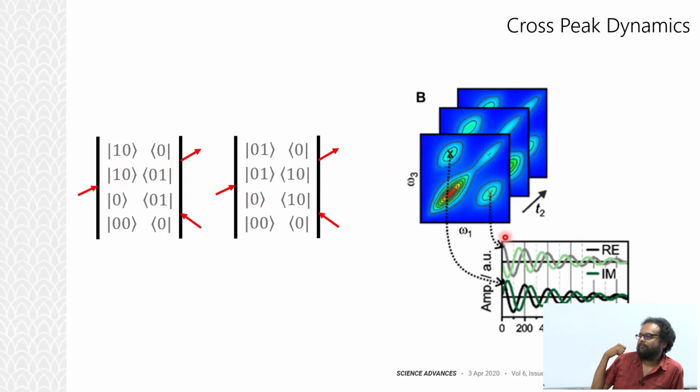Going back to what we learned in the previous class, you saw phonon spectra in pump-probe. If I take a 2D spectrum, those phonon coherences will appear exclusively on the off-diagonal features. You kind of separate it out. You can see that. That's because with the two-field interaction, you are generating a coherence, and coherence by nature will oscillate. This is my T2 or tau 2, the time delay between my second pulse and my third pulse. Now you will ask what is so important about this? Again, it's a very strong indication of the existence of coherence between two states.